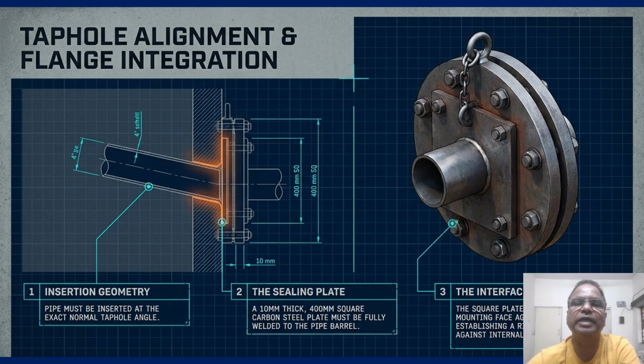Notice the 10 millimeter thick, 400 millimeter square carbon steel plate. It is fully welded to the pipe barrel to act as a sealing plate. This plate sits flush against the ABP flange, creating a rigid, leak-proof seal.